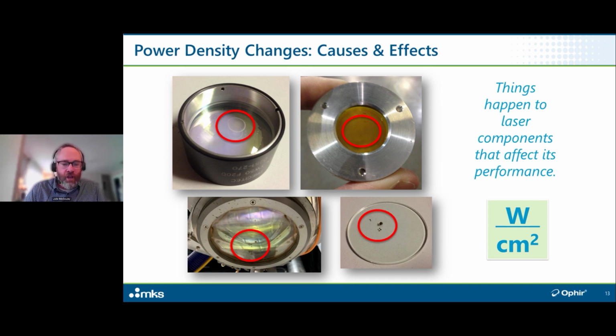I'm really specifically interested in these two bottom pictures. These are pictures that I've taken over the years of contaminated and defective optics. But these two bottom ones are pictures of cover glass that have had some kind of contamination on them that the laser has effectively burned onto the surface. Well, what's happening in that case? Number one, your laser light is being absorbed by this defect, so you are having some, albeit slight, reduction in laser power.